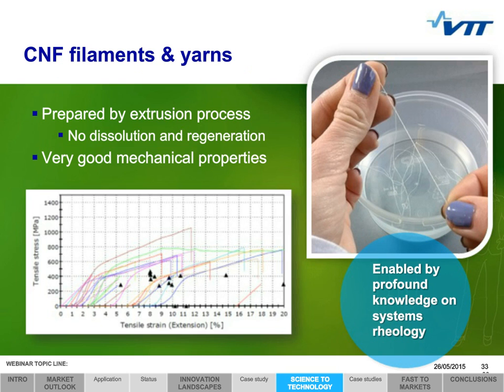CNF filaments and yarns can be prepared without dissolution and regeneration, which is typical, for example, in the traditional viscose process. This can be accomplished by swelling the cellulose nanofibrils in solution and producing filaments by extrusion. As shown in the graph, with tensile stress mapped against tensile strain, the produced filaments have very good mechanical properties.